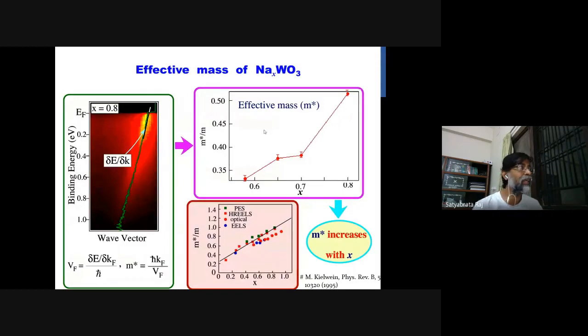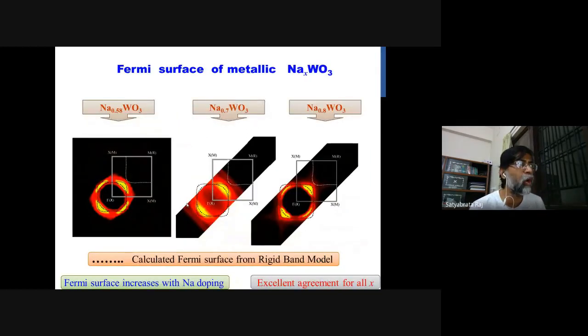We have also measured the effective mass in the metallic sample, which increases with X linearly, and which is well matching with the other experiments. Now we have measured the metallic Fermi surface. They are in excellent agreement with the different X values, and you can see this is the band-structure-calculated Fermi surface. There is no Fermi surface at the X point or M points, so it is the bulk Fermi surface.